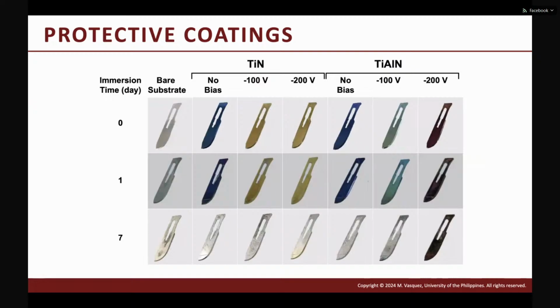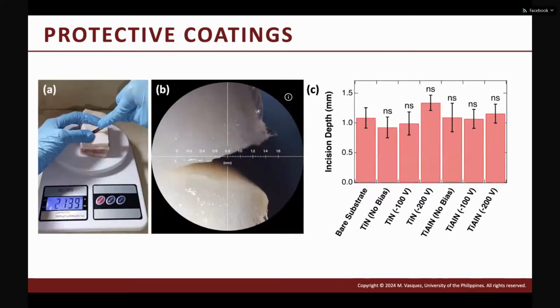So this one is just a basic scalpel blade. We just want to test if we can maintain the sharpness of the blades once we coat them, because again, the coating can protect the blades from harsh conditions. Although we know that this is disposable, we just want to demonstrate that if you coat the scalpel blades, there's no change in its sharpness, but you can improve its anti-corrosion properties. So we did the test on pig skin, and we actually have no difference in terms of its sharpness. But we improve its hardness, we improve its anti-corrosion properties, and so on.